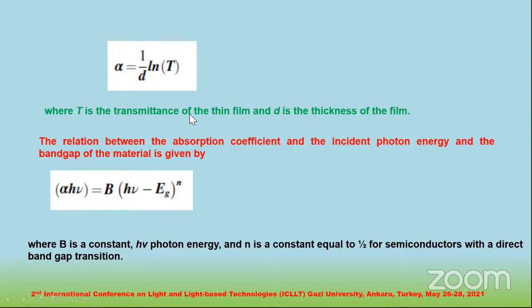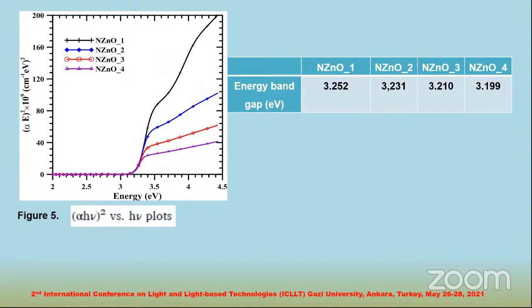The relation between the absorption coefficient and the incident photon energy and the band gap of the material is given by the following, where B is a constant, hv is the photon energy, and the exponent is a constant equal to 1 divided by 2 for a semiconductor with a direct band gap transition. The energy band gap of the film was found by plotting (alpha hv) squared versus hv, where the slope of this graph intersects the hv axis, indicating the band gap energy of the film. The energy band gap is obtained from the intercept of the extrapolated linear part of the curve with the energy axis.